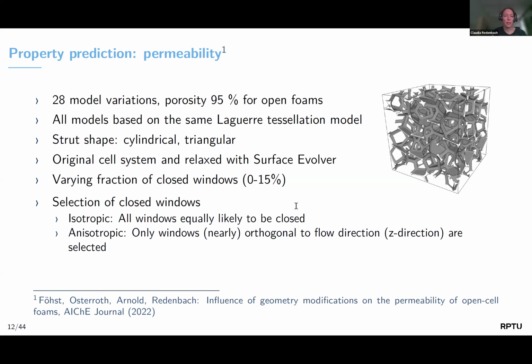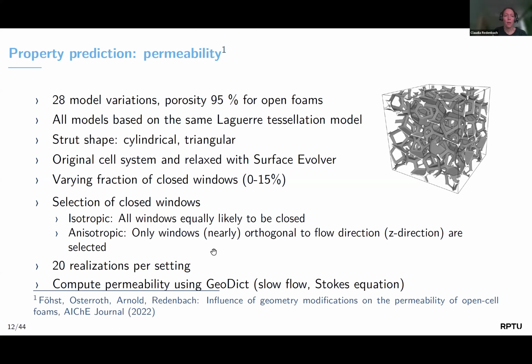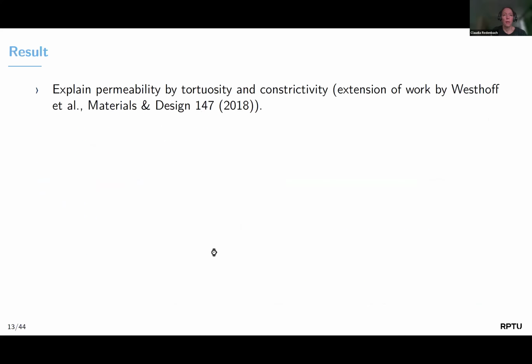When it comes to selecting how to close these windows, we chose two protocols. One is isotropic, meaning every window was equally likely to be closed. And in the other situation, we only closed them orthogonal to the flow direction, with the motivation to basically put something in the way of the cells that are flowing through our medium. We generated 20 realizations per model variation, and we computed permeability using the GeoDict software.